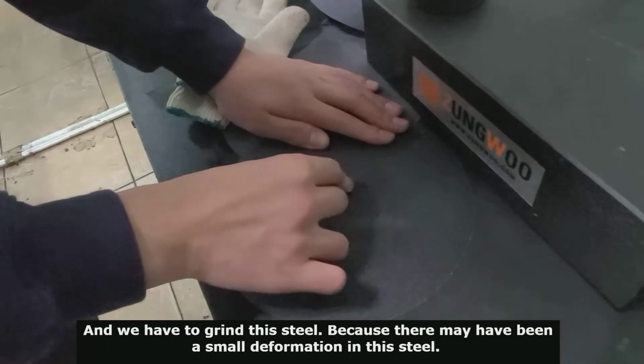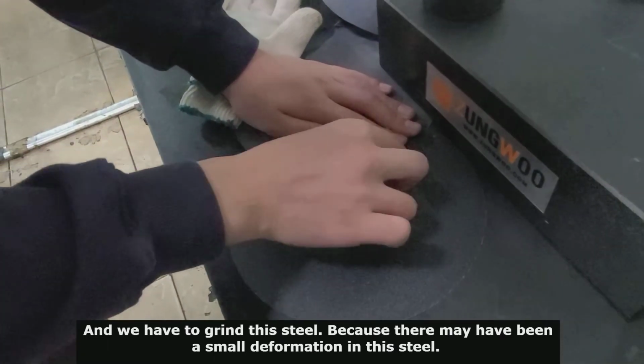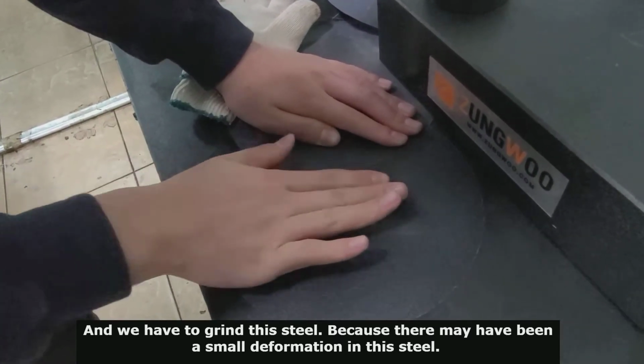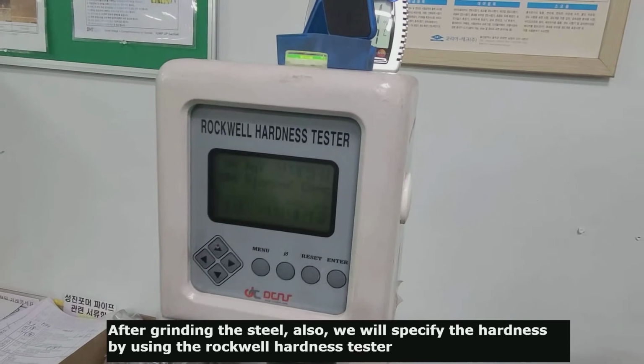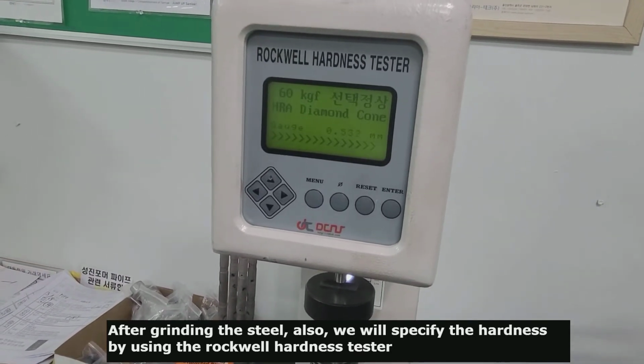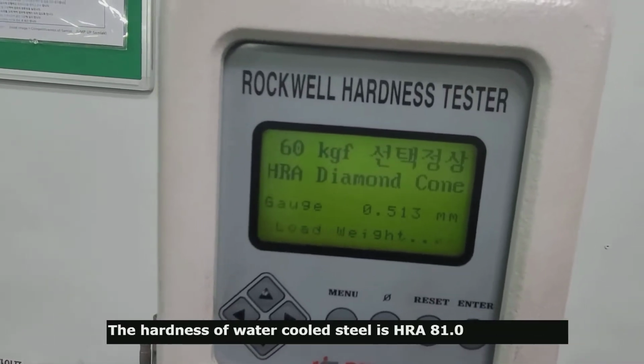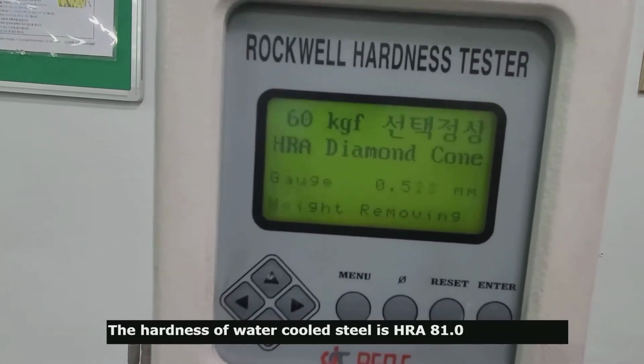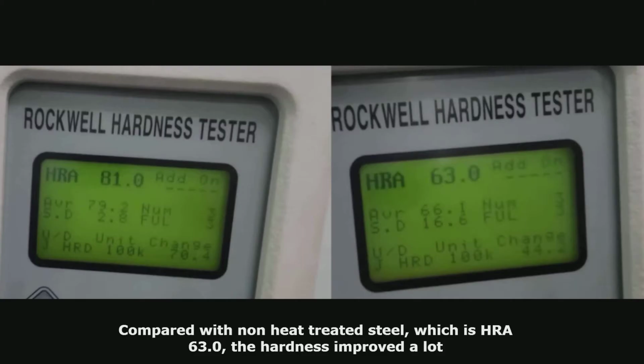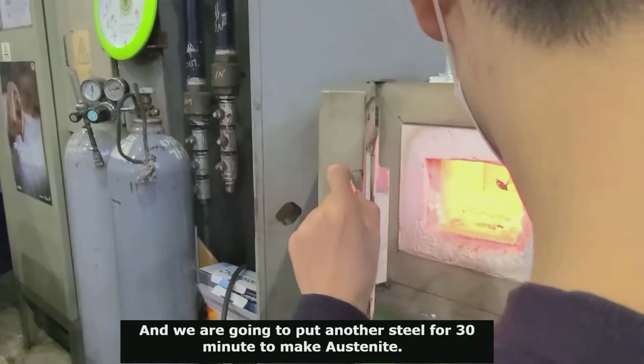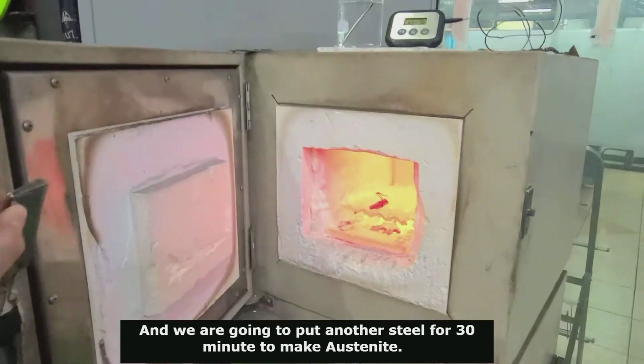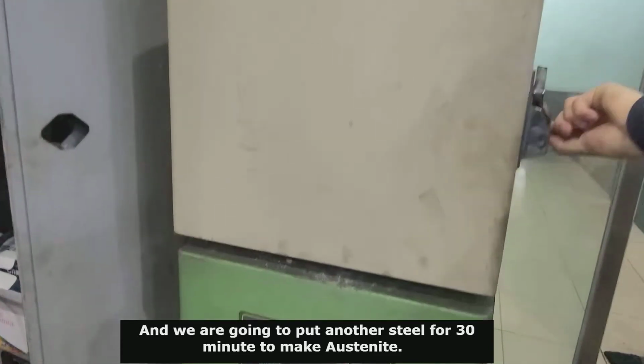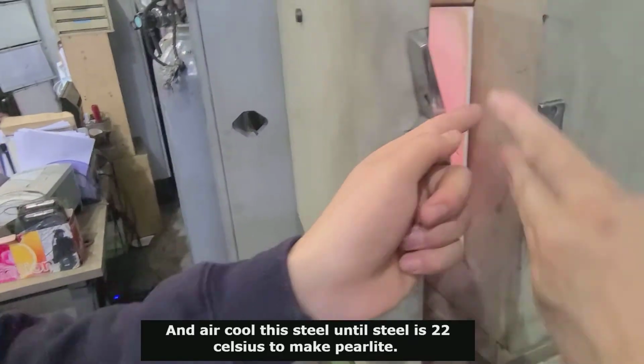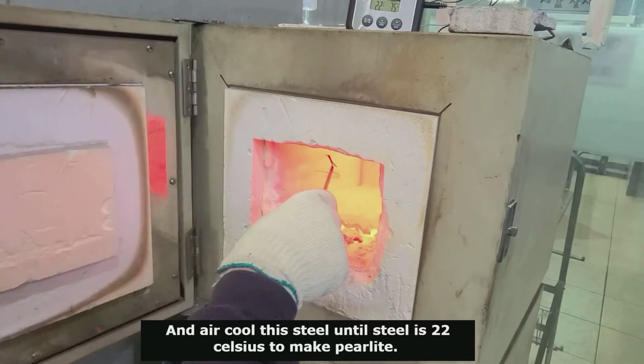And we have to grind this steel because there may have been a small deformation in this steel. After grinding the steel, also we will specify the hardness by using Rockwell hardness tester. The hardness of water-cooled steel is HRA 81.0. Compared with non-heat treated steel, which is HRA 63.0, the hardness improved a lot. And we are going to put another steel for 30 minutes to make austenite. And air cool this steel until steel is 22 Celsius to make pearlite.